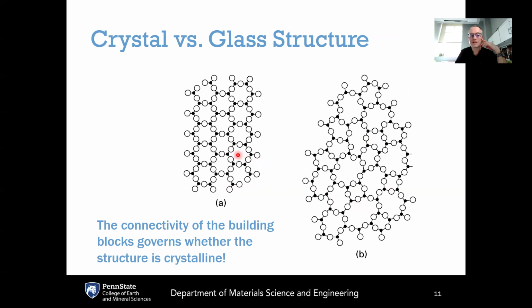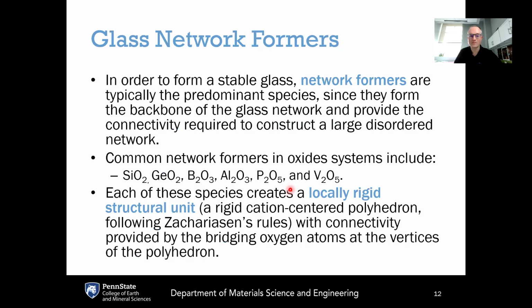One of his key insights is that even when the basic building blocks are the same, it's really the connectivity of those building blocks, how you put them together, that governs whether the structure is going to be a crystal, as on the left, or a glass, as on the right. Now, Zachariasen's random network theory was used to classify oxides as either being network formers or network modifiers, where if we want to have a stable glass, network formers are the species that follow Zachariasen's rules. Network formers are the predominant species in the formula for the glass chemistry, since they provide the backbone of the glass network, and they provide the connectivity that's required to construct this large disordered network in 3 dimensions.